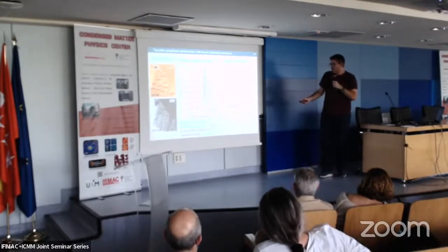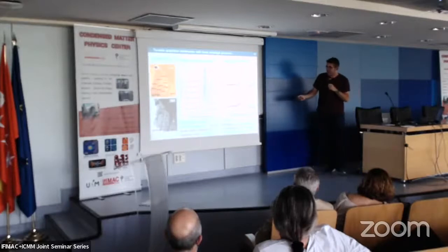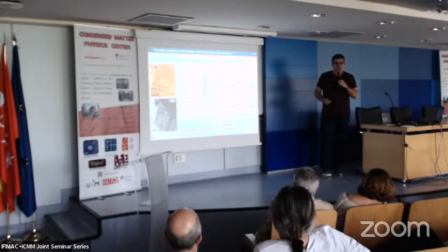But if you analyze a bit more in detail these peaks, we can see that peaks for pristine graphene can be fitted with just a single component. Okay, this is the usual thing. But if we analyze in detail peaks for higher pressure, we can see that we need an extra second component to be able to fit and explain these peaks. And this extra second component is compatible with having some carbon atoms bonded to the substrate. So this confirms what we obtained by the DFT calculations.